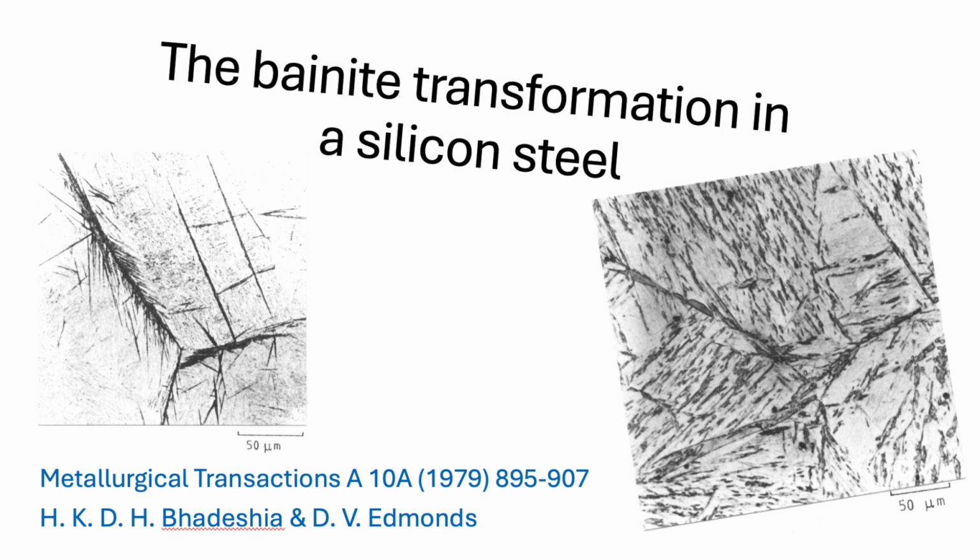And that tells us? It tells us the transformation isn't just about reaching the lowest energy state, like simple thermodynamics might suggest. Something physical or kinetic must be actively stopping it. Interesting. Okay, so what else did the timing reveal? They used dilatometry, right? Measuring expansion. Yes, to plot the TTT curve, time temperature transformation. And they didn't just find the expected C shapes for upper and lower bainites starting. This is where it gets really interesting, I remember. This is where they threw a real wrench into the works of the dominant theory at the time.